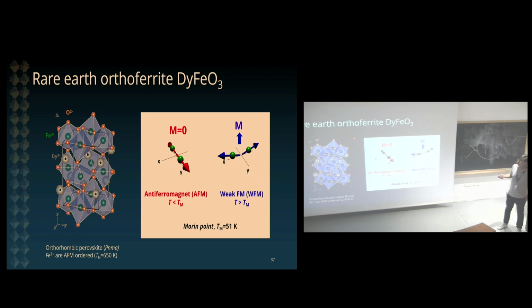So the material that we will use for this study is dysprosium orthoferrite. This is an orthorhombic perovskite system that is characterized by an antiferromagnetic order of the iron 3+ that occurs below 650 Kelvin. And we have the typical orthorhombic Pnma structure. However, at low temperatures, there is a purely magnetic transition to a low temperature collinear antiferromagnetic state, which is depicted here.